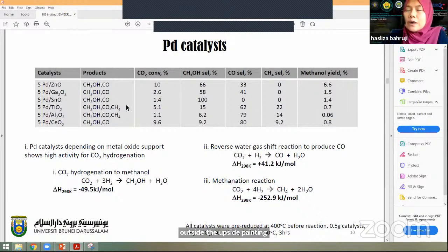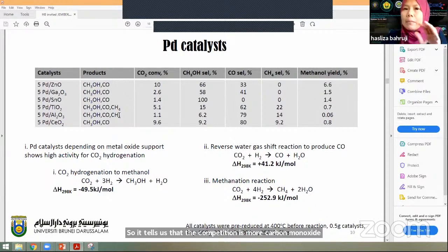Now, what we can see here is that the products are mainly carbon monoxide and methanol. But when we have titania and alumina, we start to see methane also being produced. So it tells us that the competing reactions are carbon monoxide and methanol, but methane is only produced when we have a certain type of metal, a certain type of active site, that can create this methanation active center.